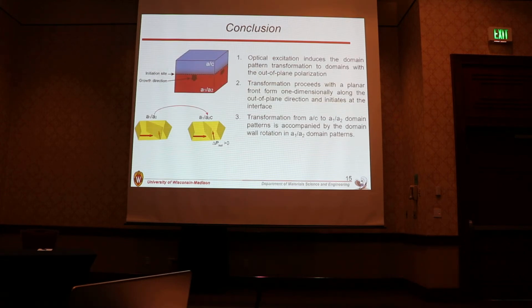In conclusion, we have found that the optical excitation can induce the domain pattern transformation from a1/a2 to a/c domain patterns. And this growth mechanism can be explained with the one-dimensional planar front growth mechanism, and the growth direction is along the out-of-plane direction. And we reasonably think that the initiation site is an interface between AA and AC domain patterns. And by measuring the domain wall angle changes, we found that the transformation proceeds with the polarization switching in one domain in these domain patterns.